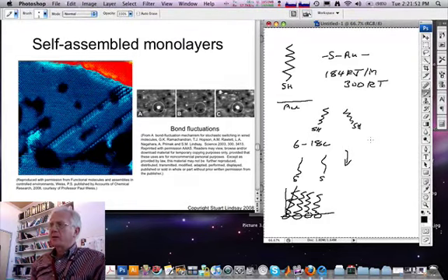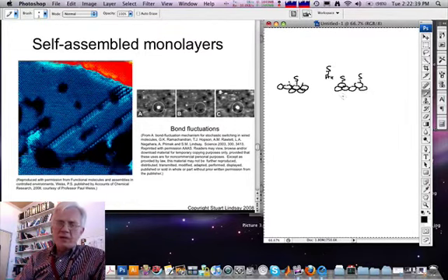So how come these molecules are mobile? Well, it's still something of a topic of debate, but the most likely picture is that on the gold 111 surface, when a sulfur adds to the surface, it does indeed form a strong bond to the gold atom that it bonds to, but this weakens the interaction with neighboring golds. So the mobile unit is actually an SAu, and most likely what it does is to move around on the surface until it forms a structure somewhat like this, which is then densely packed.